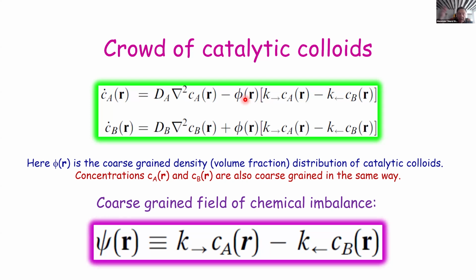And therefore, in a coarse-grained sense, where the distance is larger than the distance between these colloidal catalysts, you have these two diffusion equations. Again, fuel molecules diffuse with their own diffusion coefficient, and exhaust molecules diffuse with their diffusion coefficient, but with a rate proportional to the concentration of colloids, you have a chemical reaction that occurs on every colloid surface. So in fact, this suggests that the key player here is a quantity which I call the field of chemical imbalance. We decided that this chemical imbalance is non-zero at infinity, but now it will depend in some way on the place, on coordinate.